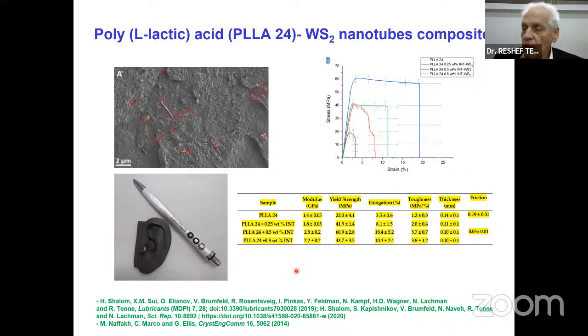Why is that important? Because you think carbon nanotubes will solve all the problems of reinforcing polymers. No, there are problems that carbon nanotubes or graphene cannot solve. First of all, graphene and carbon nanotubes tend to agglomerate dramatically. And these nanotubes do not, because they don't have pi-pi stacking forces. And so they are, of course, weaker in terms of mechanical ability, but they are very strong, and strong enough, about 100 times stronger than the polymer, so as to be able to reinforce the polymer.